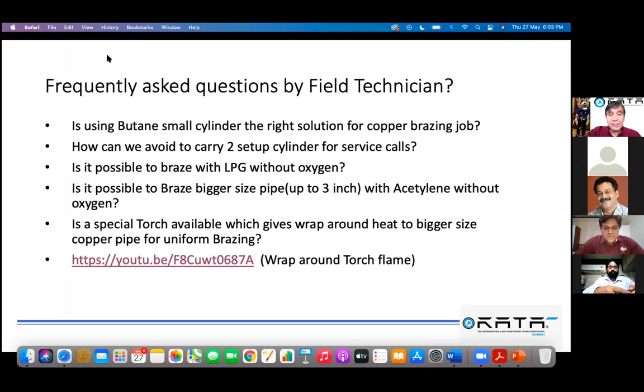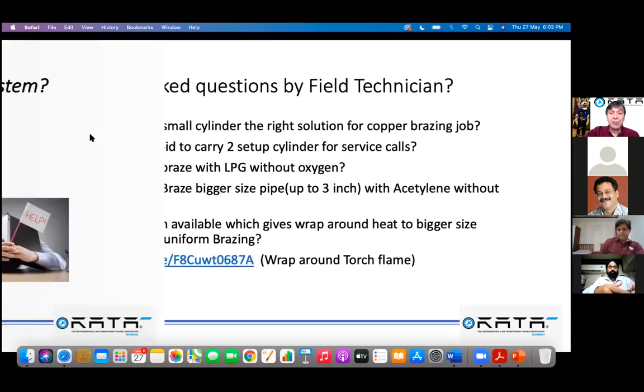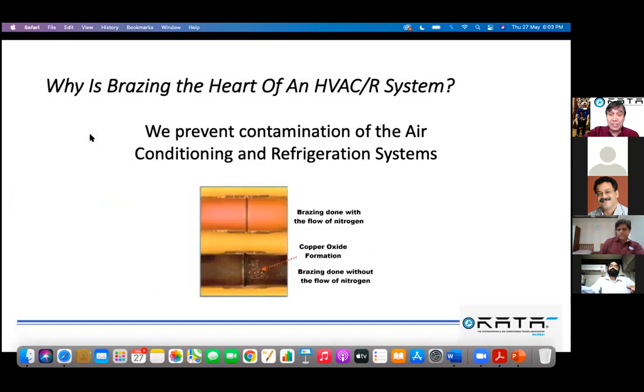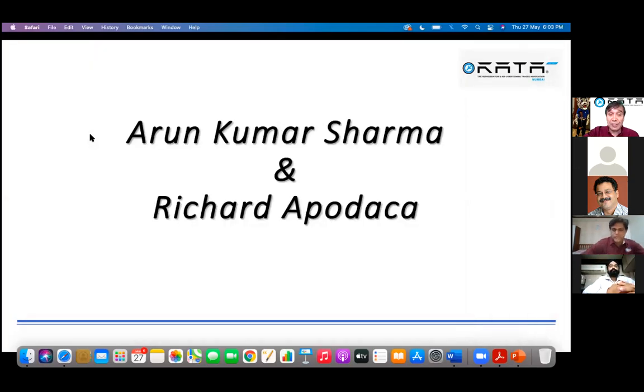So cleanliness of the tube, the proper size diameter, that it's uniform through the 360 degrees of the copper tube, and the uniform heat, the proper heating that you get around the entire copper tube, that ensures that you get the capillary action that is required to have that strong brazing joint, so that you don't have leaks with minor vibrations, and you have a good, healthy system.